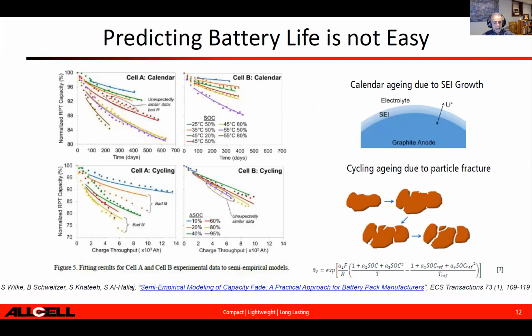We've done extensive study with the National Renewable Energy Lab. We published that work, and you'll see a lot of this. This is not unique to us. Most people in the electrochemical field or batteries understand that you can actually quantify the effective temperature, C rate, depth of discharge, and use that with a smart battery management system to actually maximize the life of the battery by both controlling the operating condition, but also by controlling the window that you operate the battery to give you the desired life, cycle life, or calendar life.